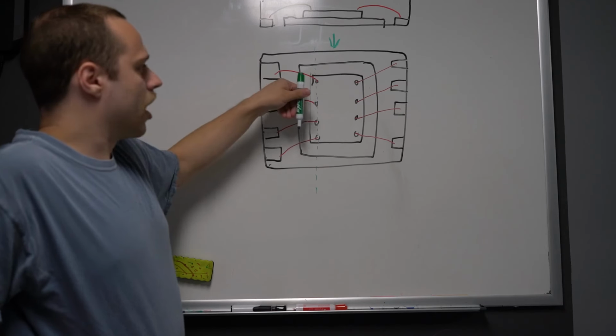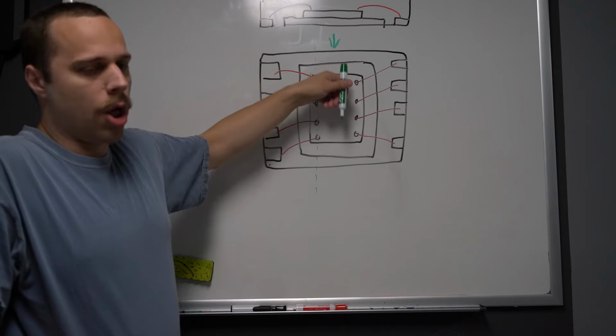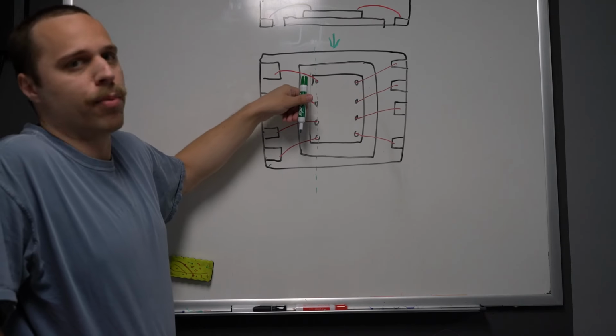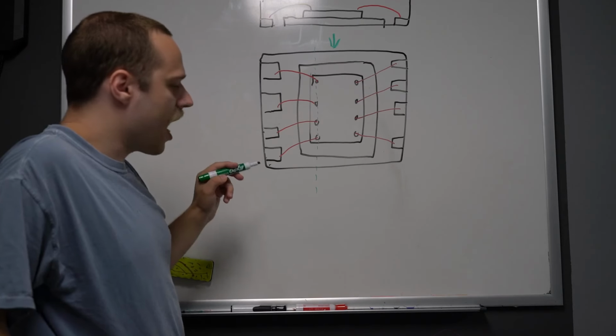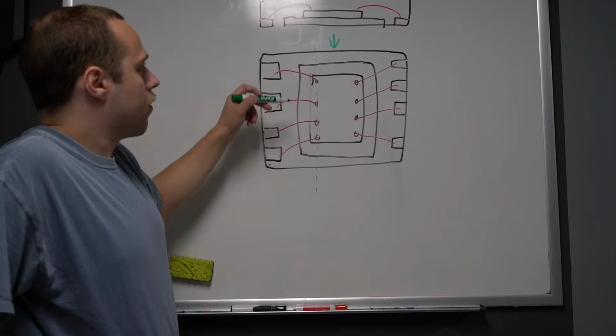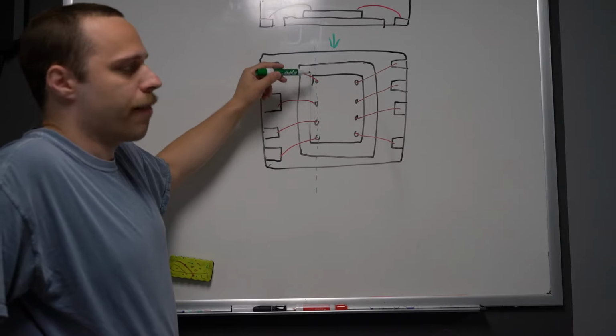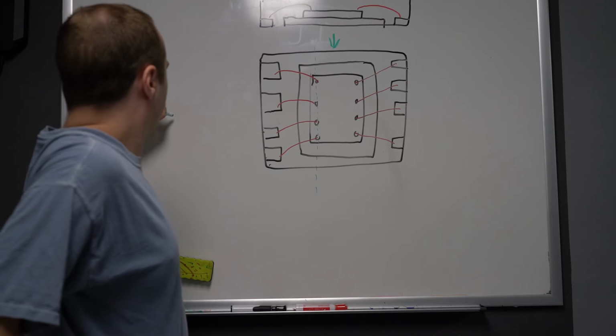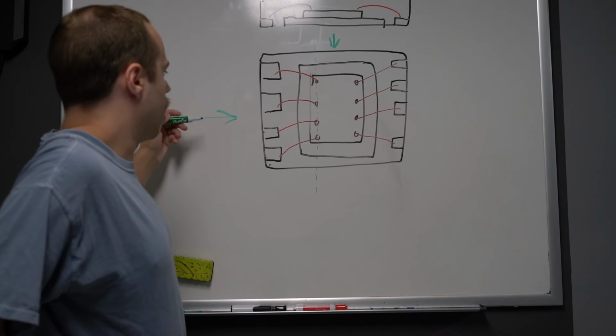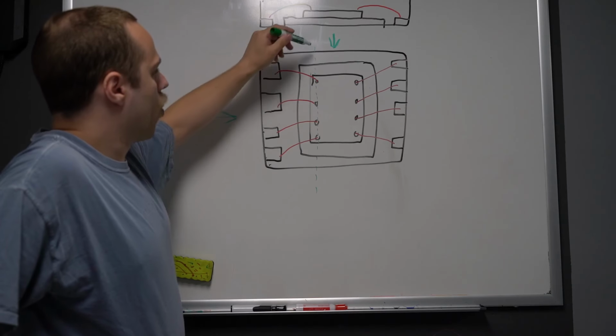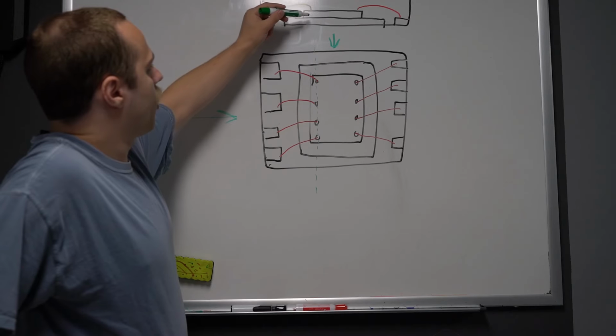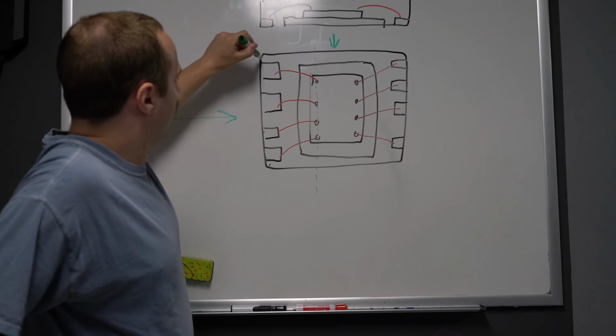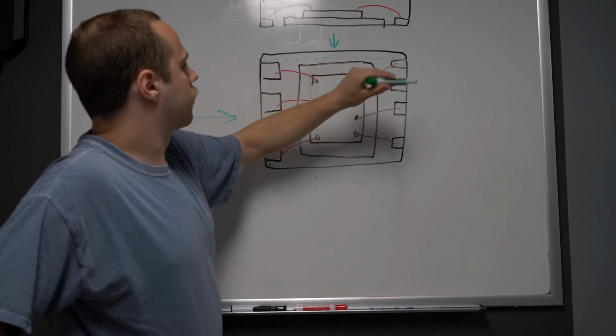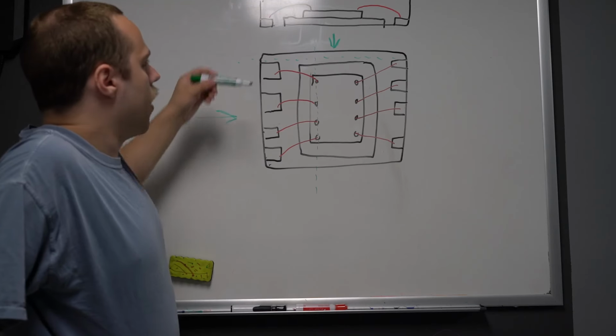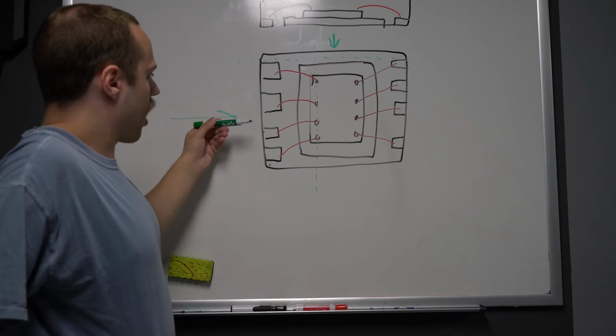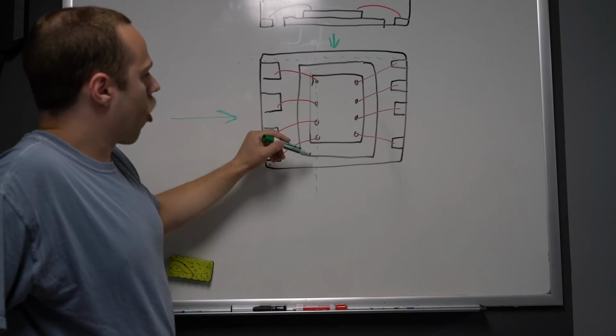But generally, along an edge of the device, the wire bonds are all in a line. They're usually essentially as close to the perimeter of the die as you can get. And so in order to maximize the chance of getting potentially a couple of bonds in cross-section, we're going to do the cross-section from this plane, looking in. So we're going to want to section this way rather than in this view, which would be like this, obviously lower down. Rather than sectioning this way, we're going to section this way, and so ideally try and get a couple of bonds.